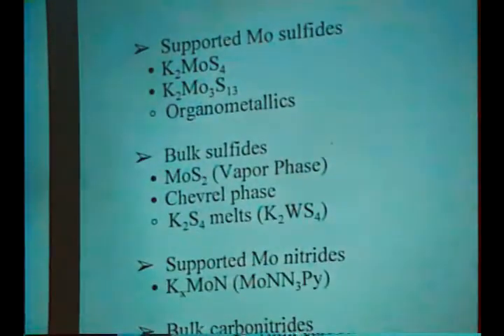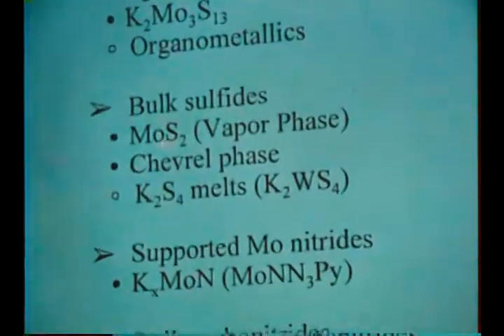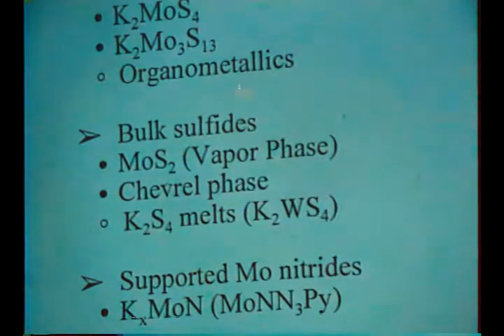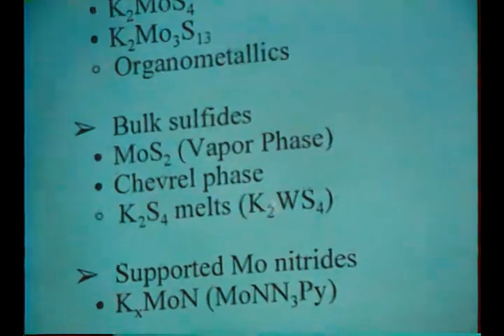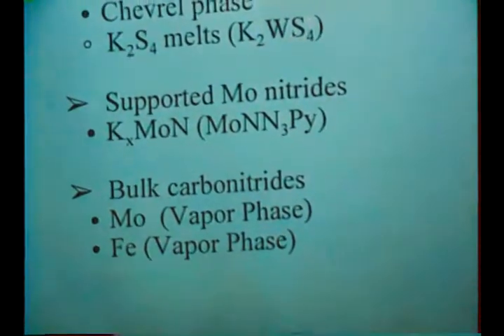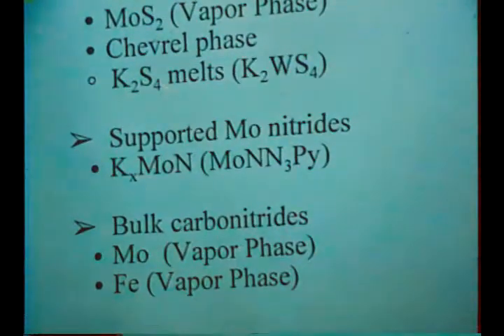Something about my convention here. The solid dots are those that have been analyzed for their catalytic activities. The rings are those that have not been analyzed. In the bulk sulfides, specifically this is where we're going to be today, looking at making molybdenum disulfide with the vapor phase technique. We've also been looking at making Chevrel phase compounds and looking at their catalytic activities, and also making materials using a potassium sulfide polysulfide melt. And actually specifically making the potassium thiotungstate and other metal sulfides with this process.